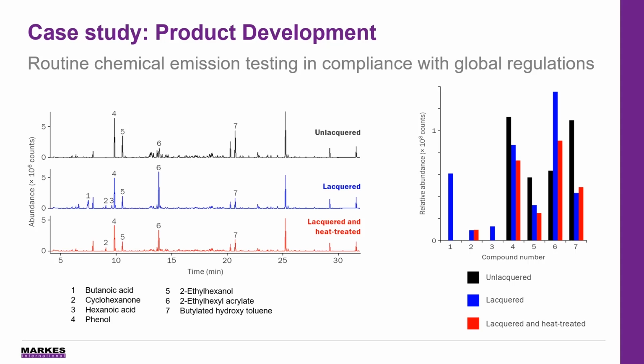What we have here is an example of using the microscale chamber for product development. This was a sample of flooring that a manufacturer was having trouble with complying with regulations. So if we look at the information in front of us, we had the sample, which is shown in the top black trace, which was a piece of flooring material that had no lacquer treatment and no heat treatment. And what the manufacturer thought is that perhaps the lacquering and the heat treatment would be able to reduce some of the emissions of volatiles that were regulated.